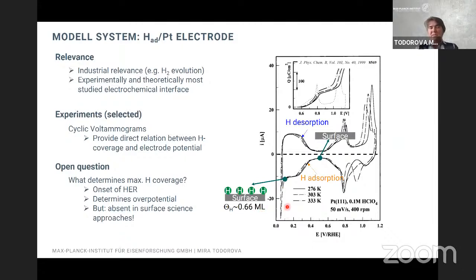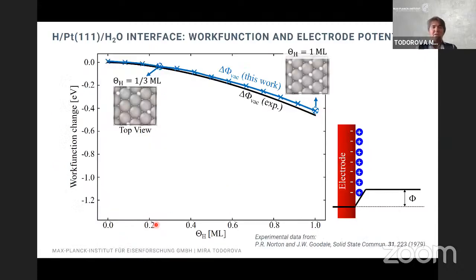So what we wanted to understand is what determines this maximum coverage. So what leads to this onset of the hydrogen evolution reaction, and why couldn't this be explained in surface science approaches, so basically, if we neglect the water. In order to do this, we performed density functional theory calculations for this interface. We use, for the experts, the RPBE functional, which is a GGA functional. And we looked, first of all, just at the work function change in vacuum as we put more and more hydrogen on the surface. I would like to point out that our reference here is just the work function of the clean platinum surface.